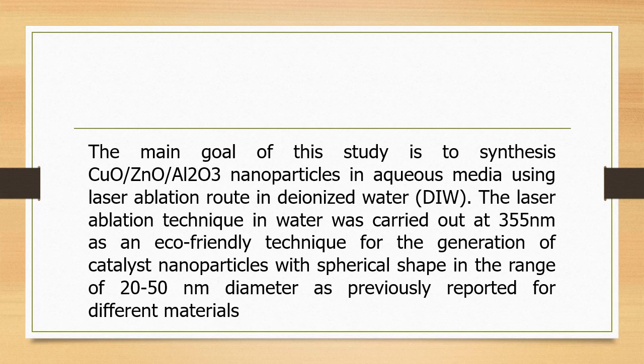That is an eco-friendly technique, in other words, environmentally safe. And the generation of catalyst nanoparticles has a spherical shape. The range of nanoparticle diameters is about 20 to 50 nanometers, as previously reported for different materials.